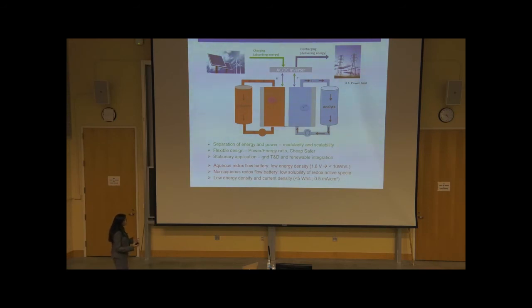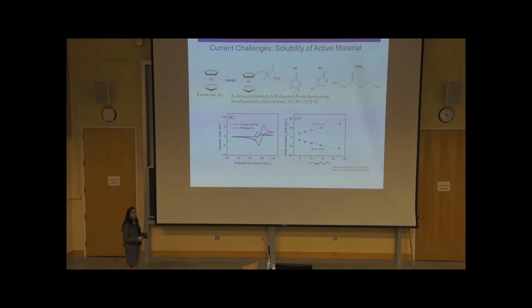And unfortunately, none of the non-aqueous redox flow batteries can match the energy density of aqueous redox flow batteries because of the extremely low solubility of these redox active species. That's why their energy density and current density is very low. So the major challenge in non-aqueous redox flow batteries is to increase the solubility of redox active species. And ferrocene is one interesting system, but its solubility is very low.